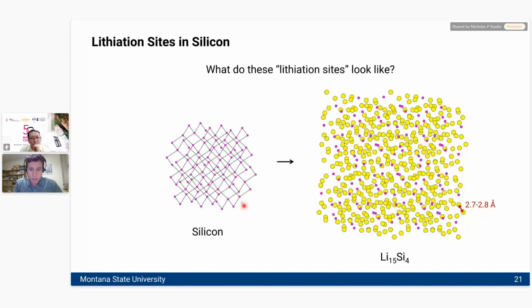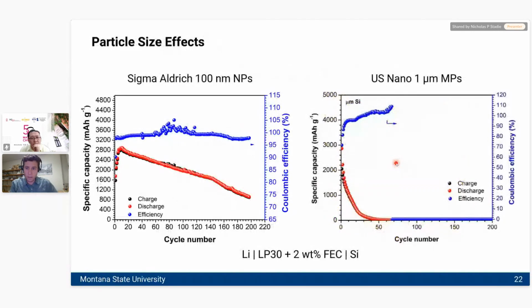You'll notice that I've not drawn any silicon bonds because every single one of them in the original silicon lattice, each silicon distance, is far too long to be considered as any kind of a bond. This is a completely different material. It's basically a sort of alloy at this point, and you break and make every single one of those silicon bonds every single time you charge and discharge this material.